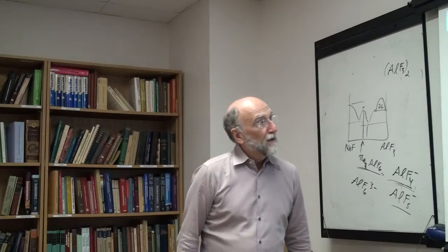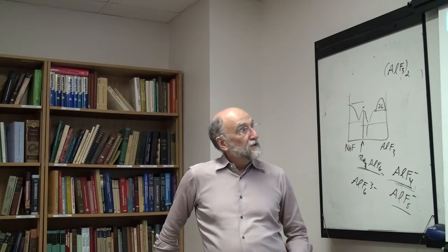I'm talking about salts, and I'm dealing mainly here with the halides, because the same thing with complexing would apply to other salts like sulfates and nitrates and so on. But once again, these are big anions, and as I said before, when the anion becomes big, interactions become weaker, and you have less tendency to order. So when you're dealing with other anions like sulfates, nitrates, and so on, the complexing is generally very small.